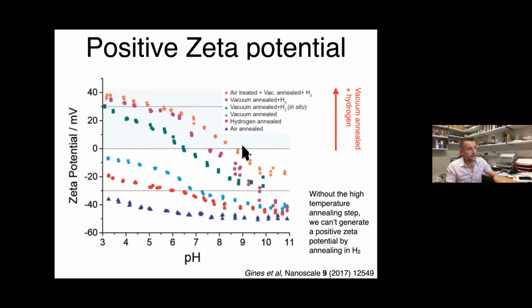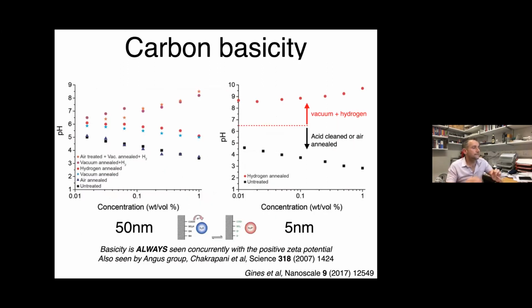But if I generate the sp2 and then anneal it in hydrogen gas, it goes positive, right? So I think this is really important because we don't see this positive zeta potential without the sp2 bonding in this case. And the thing that really made it clear to me, well, maybe not so clear, but convinced me a little bit more, shall we say, is the basicity. So going back to the COOH groups, let's just talk about the clean particles before we've treated them in hydrogen, right? They're COOH terminated, right?